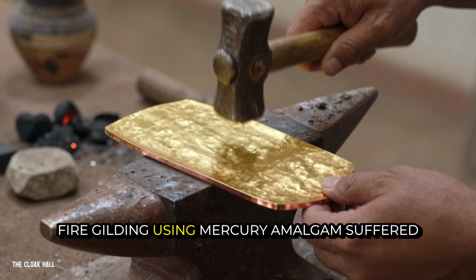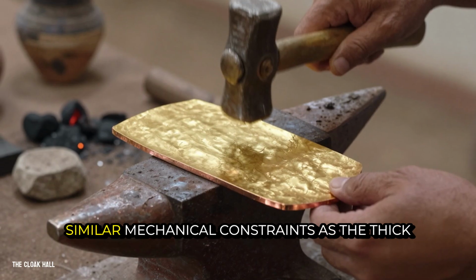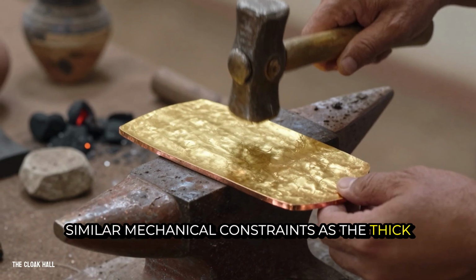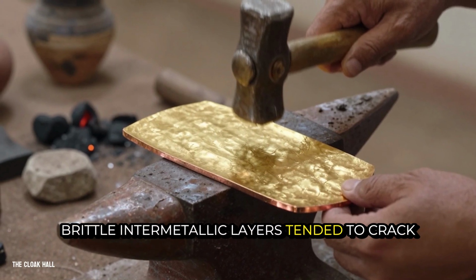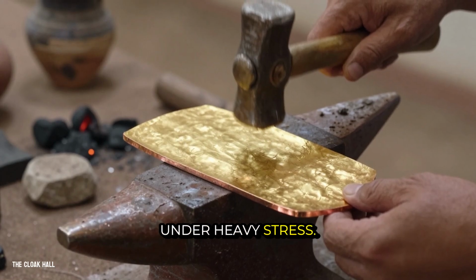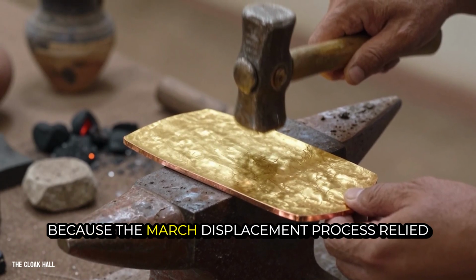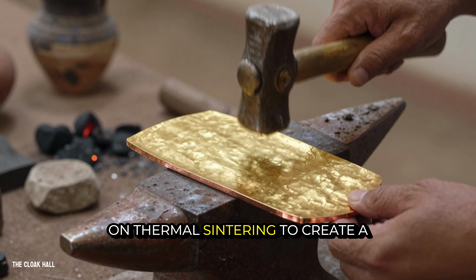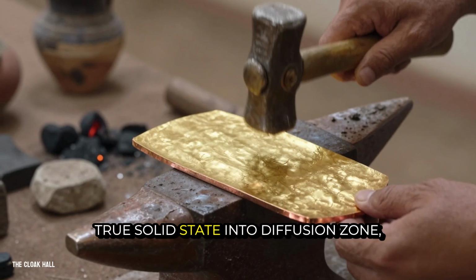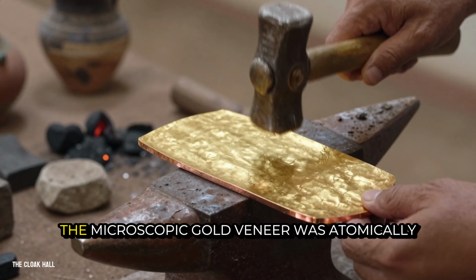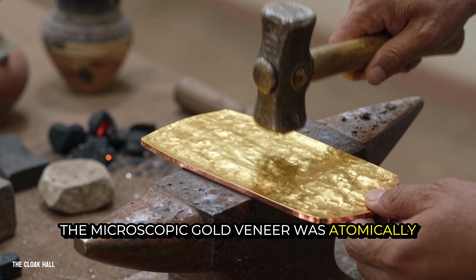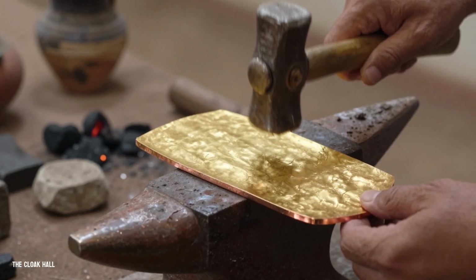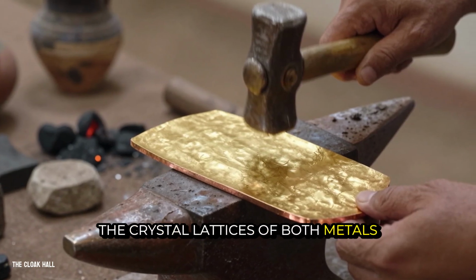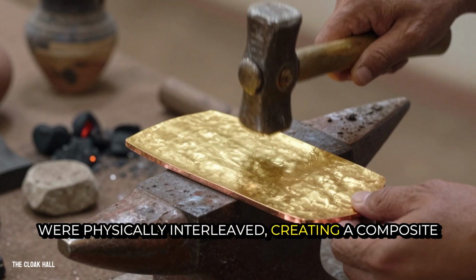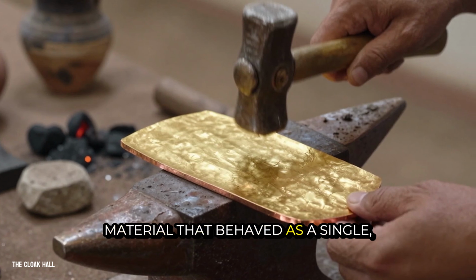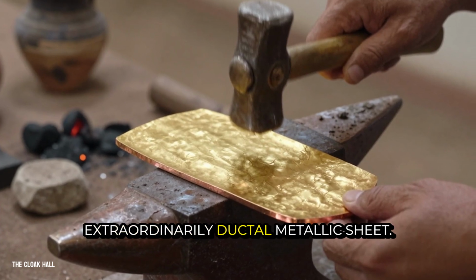Fire gilding using mercury amalgam suffered similar mechanical constraints, as the thick, brittle intermetallic layers tended to crack under heavy stress. Because the Moche displacement process relied on thermal sintering to create a true solid-state interdiffusion zone, the microscopic gold veneer was atomically bonded to the copper base. The crystal lattices of both metals were physically interleaved, creating a composite material that behaved as a single, extraordinarily ductile